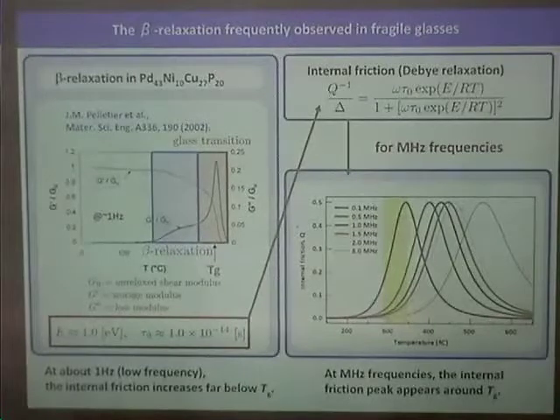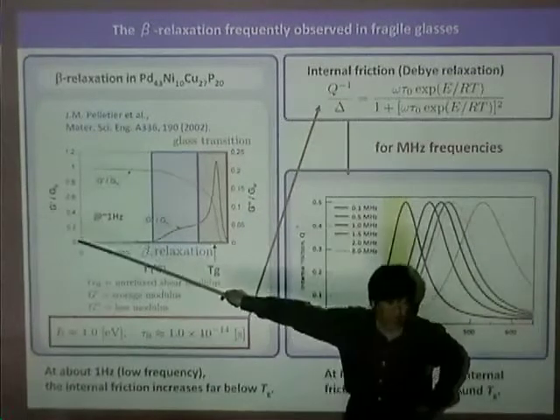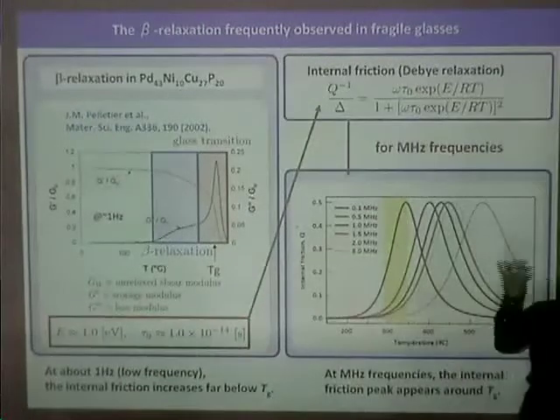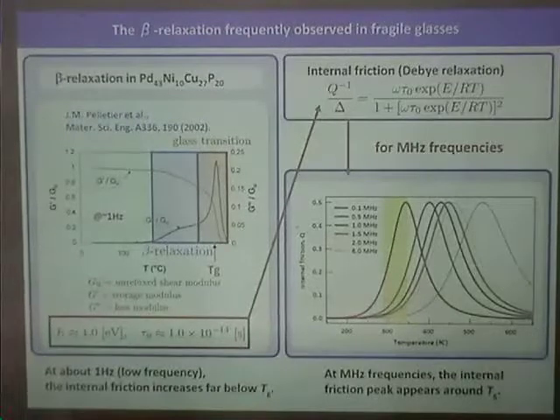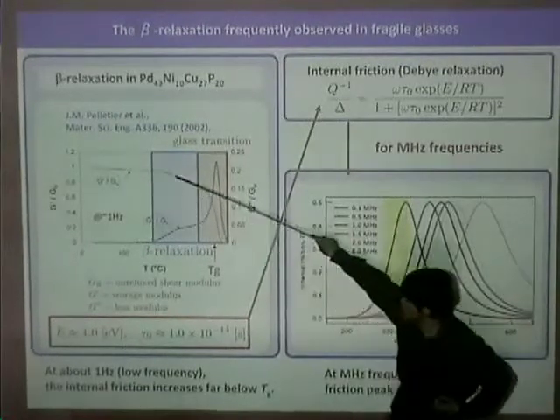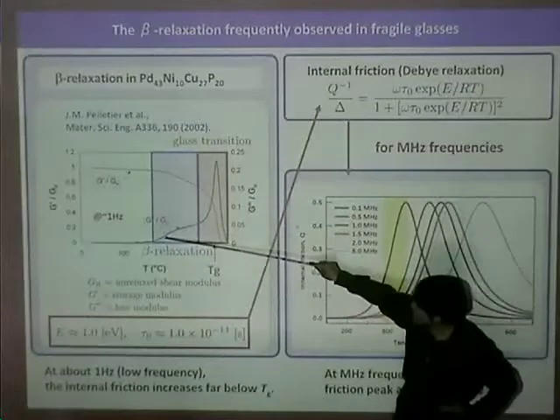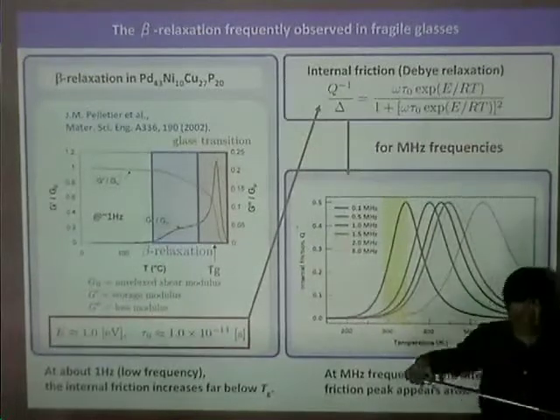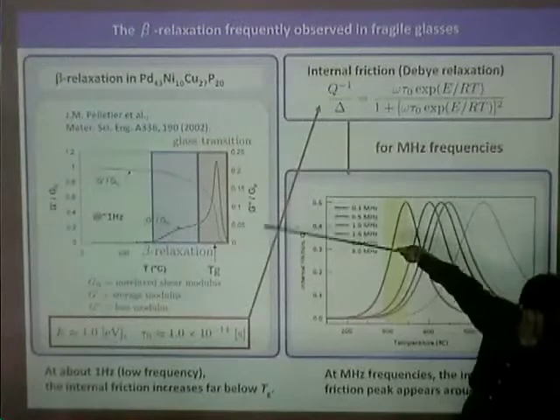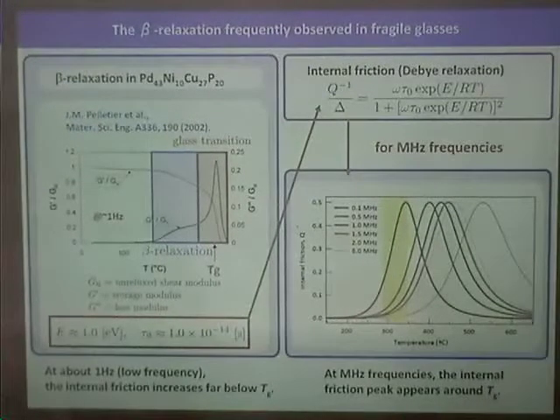Can you say very briefly what you mean by internal friction and how it's related to G double prime over G prime? G prime is the storage elastic modulus, and G double prime is the loss modulus, the imaginary part, which corresponds to the internal friction. The elastic constant G prime decreases towards the glass transition, and G double prime increases. Q inverse is almost equivalent, the ratio of the loss to the storage modulus.